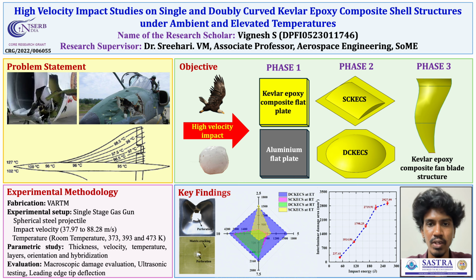In phase 1, the Kevlar-Epoxy composite laminates were impacted at both room temperature and elevated temperature and compared with aluminum flat plates to understand the damage behavior of the Kevlar-Epoxy composite laminates. In phase 2, the single curved Kevlar-Epoxy composite shell structure, that is SCKECS, and the doubly curved Kevlar-Epoxy composite shell structure, DCKECS, were impacted and analyzed. To understand the realistic impact damage behavior, we fabricated and analyzed gas turbine composite fan blades in phase 3.